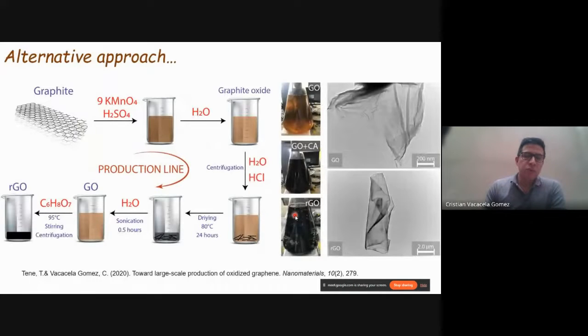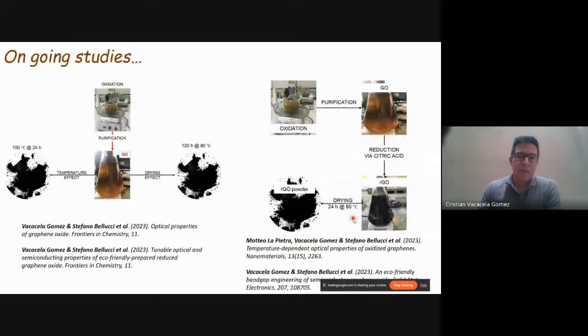In our work, we follow a similar approach to prepare graphene oxide, but we use just potassium permanganate and sulfuric acid, and we remove sodium nitrate or orthophosphoric acid from the chemical process. Again, the idea is to get graphene oxide, and after applying, for example, citric acid, we can prepare reduced graphene oxide. As you can see, we have a lot of methods to prepare graphene oxide samples, which we will discuss in more detail later on, and also reduced graphene oxide samples.